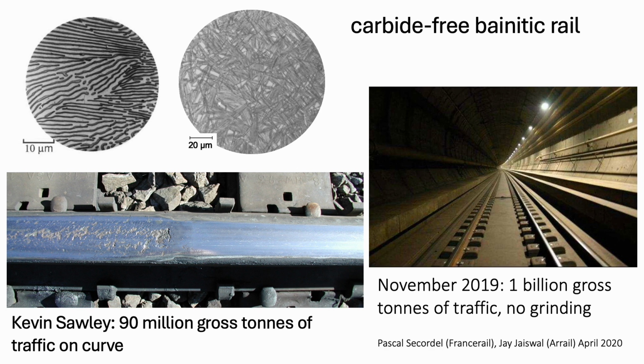The rail and car comparison highlights a recurring theme in my lecture today, that we can reduce CO2 emissions by making the optimum use of steel. Now, rails suffer from two main issues. The first being wear, so you need a certain amount of hardness relative to the hardness of the wheel and the load. The second is more pernicious, rolling contact fatigue, and this is due to a combination of torsion and compression under the rail surface during the passage of a wheel over the surface. And that eventually accumulates to propagate fatigue cracks, which lead to spalling and possibly even greater disasters.